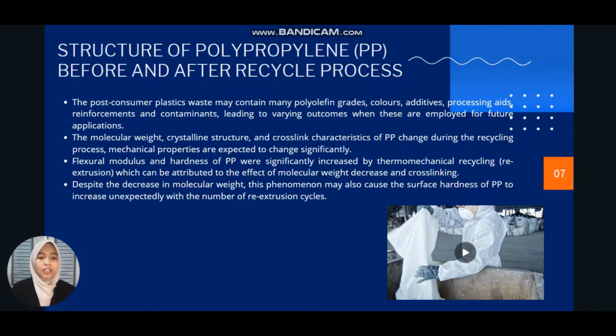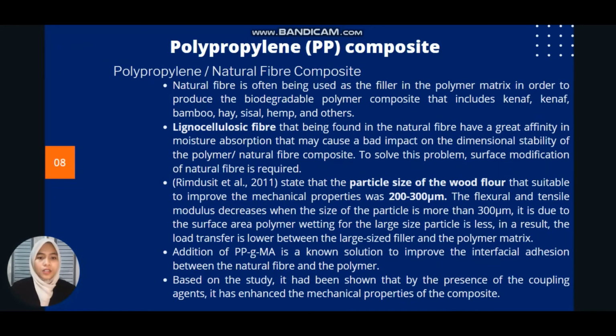So the modulus and hardness of PP will significantly increase by mechanical recycling, but the tensile strength will decrease. Then the decrease in molecular weight, this phenomenon may also cause the surface hardness of PP to increase unexpectedly with the number of re-extrusion cycles. So next is polypropylene composite. So in this study, we had studied 3 types of composite, which are PP natural fiber composite, PP mineral composite, and PP fly ash composite.